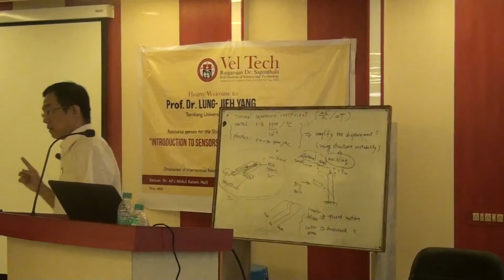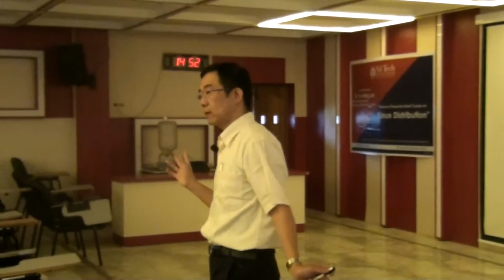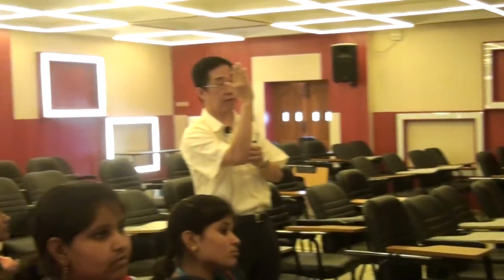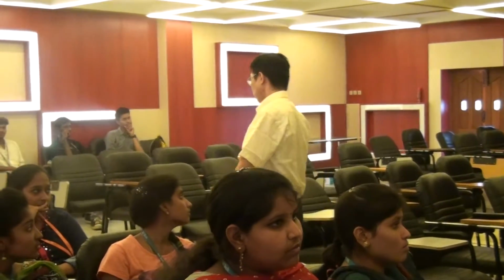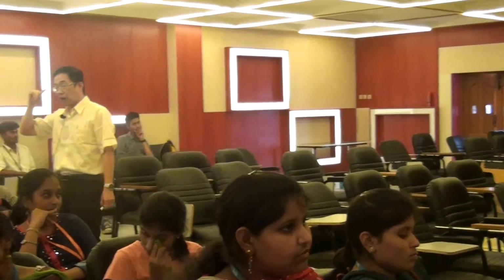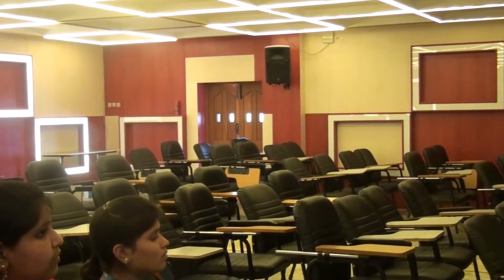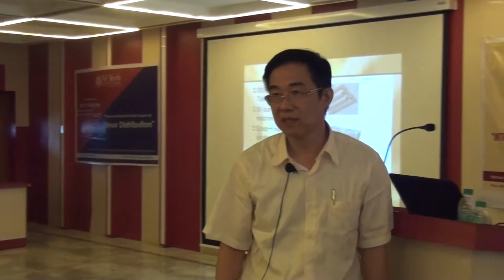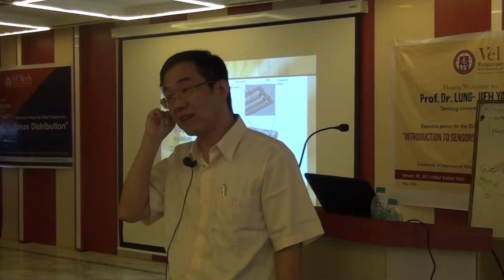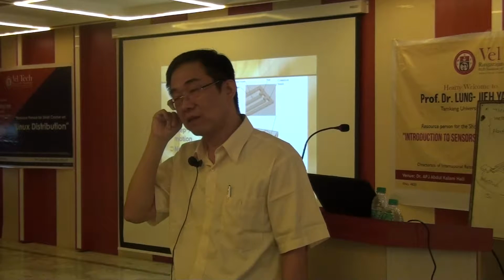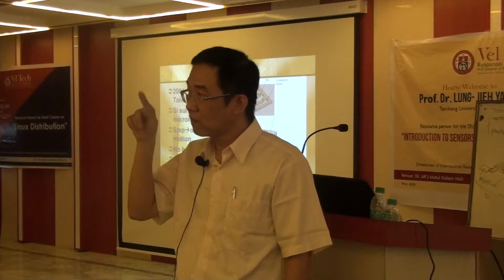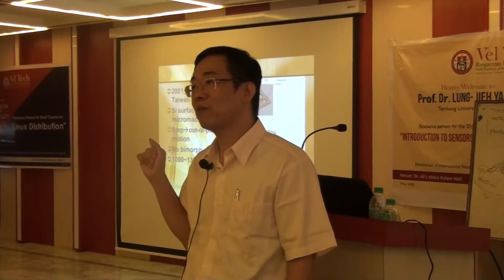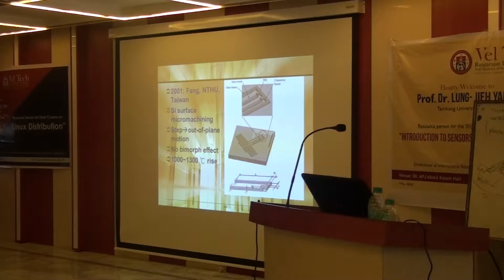What problem? The temperature is too hot. We have not mentioned the temperature. We just say heating. Okay, heating. You want to heat it until it starts to buckle the micromachine. How high? At least 400 or 500 degrees C. Or even for this case, you can see 1,000 degrees C, or even 1,300. You know how high that is? What is the melting point of silicon? The melting point of silicon is 1,450 degrees C. So just a little bit lower than the melting point of silicon.